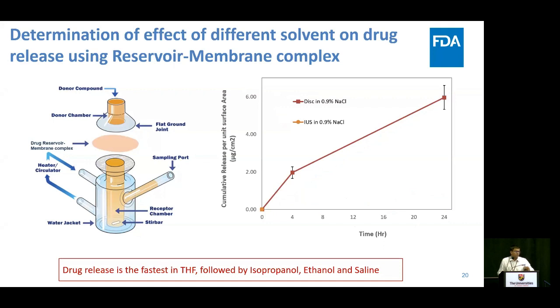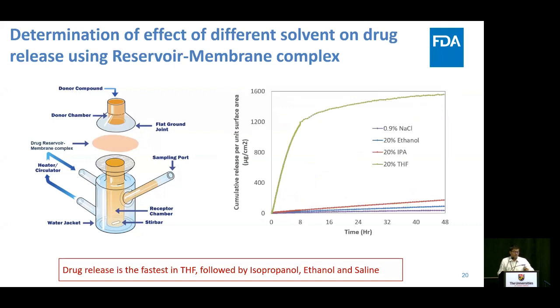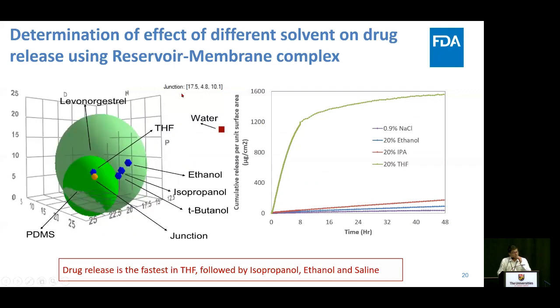And then also we use THF, and here you can see that the release in THF is really faster compared to others. And this explanation also goes back to the HSP analysis, as I've said that THF will be a good solvent because this is within the solubility sphere of the drug and polymer both, and that's how it changes the release mechanism of the IUS device.